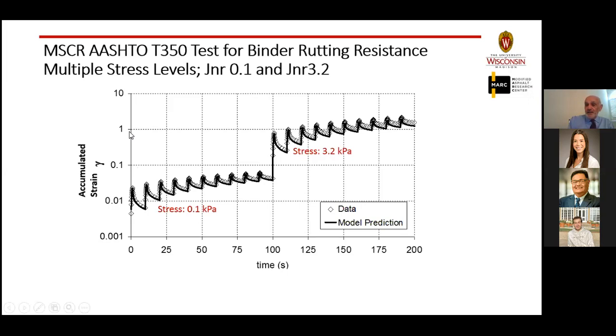And with many of these binders, when you use the MSCR and calculate the Jnr, you will actually find you are in the thousands of percent of strain. And as far as I can tell, a lot of agencies, a lot of very experienced people in this business really like this test, because finally they can see significant differences in the behavior and they can relate them much better to the actual mixture rutting performance.